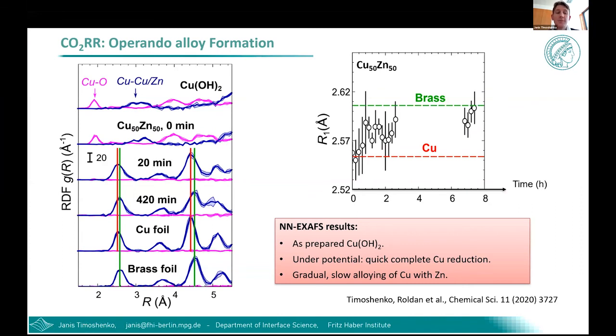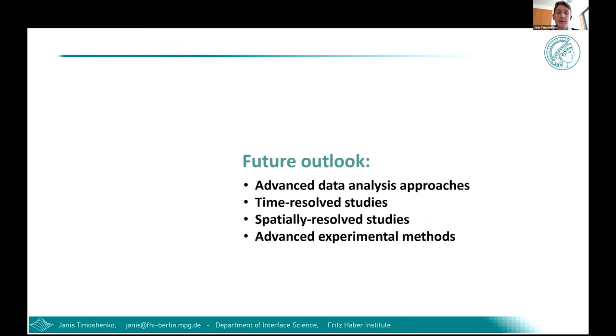But that's not the end of the story. If you look carefully enough, after 7 hours under reaction conditions, we observe that all these peaks, all the interatomic distances, are shifted towards larger distances, which is a clear fingerprint of alloying, which takes place within about 6-7 hours in this material. And it's nice to see that the characteristic time for these changes matches very well the characteristic time of changes in catalytic properties that we observed in the previous slide. So these two processes clearly are intimately linked. This particular study illustrates quite nicely the possibilities provided by advanced data analysis approaches and machine learning for the interpretation of subtle fingerprints in our EXAFS spectra due to transformations of our catalyst under reaction conditions.